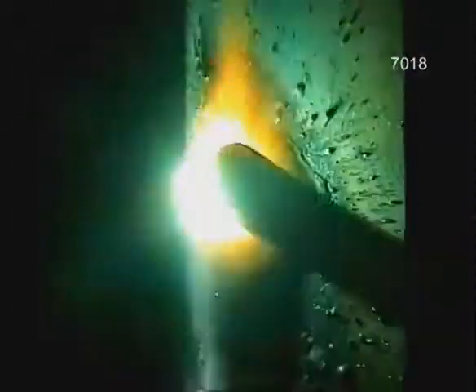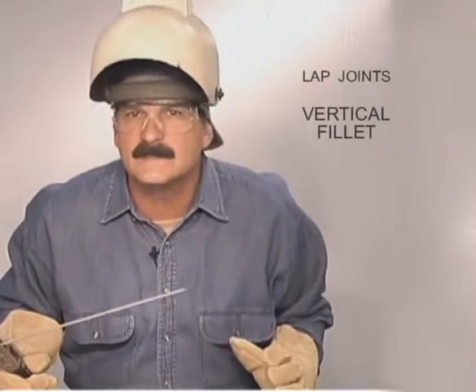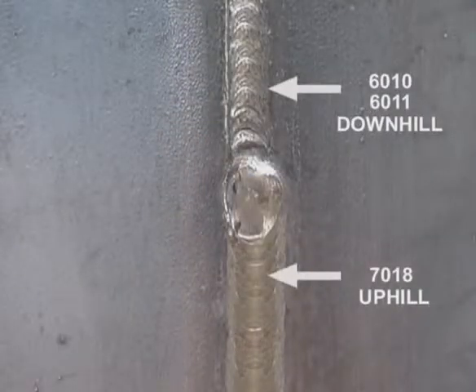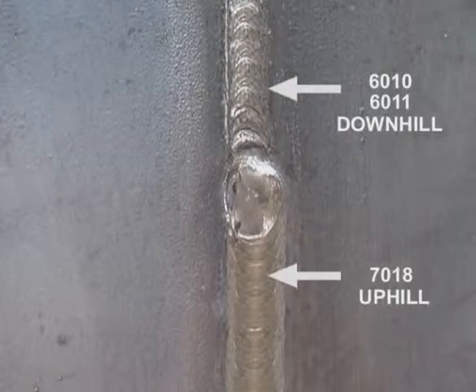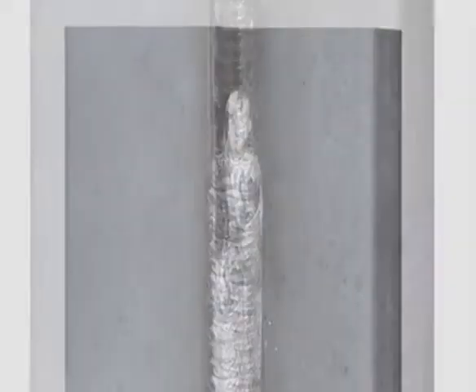puddle to tie in. If you have any trouble running an uphill fillet with 7018, try starting out with a 3/32 diameter welding rod. The smaller puddle is easier to control. You can also try stepping in a downhill pass of 6010 or 6011 first. This not only provides good penetration, it fills in the corner, making it easier to maintain a uniform arc gap for welding uphill. For heavier metal and more weld buildup, you can either stack weld beads side by side or use a weave bead. Lap joints in any position are fairly easy to weld.